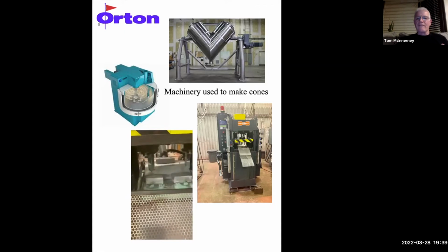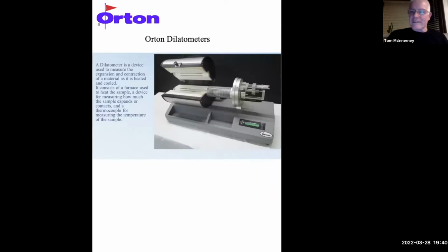So what you saw there is we're making 4 cones at a time, 2 cones per cavity. And the reason for that is when the cones are formed as pairs, we can control the density in the cone so that the edges along the die cavity have a lower density than the center of the cavity. So when you break those 2 apart and mount them on your plaque, the side that has the least density will be the bending face of the cone. So we figured out that you can actually control the directional bend of the cone by forming them as pairs where the bending face sets on the wall of the die cavity. Interesting little snippet for you.